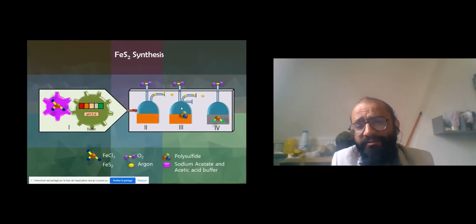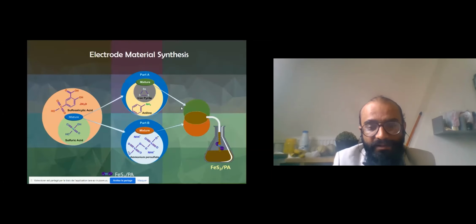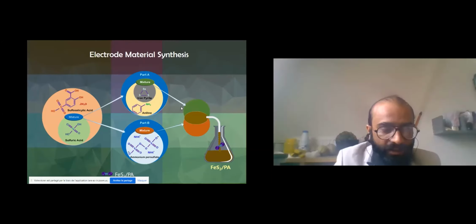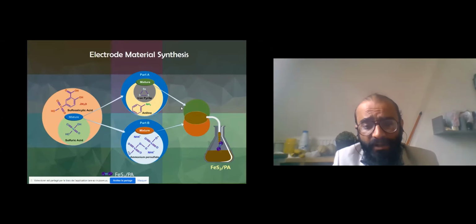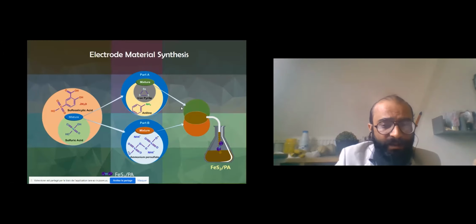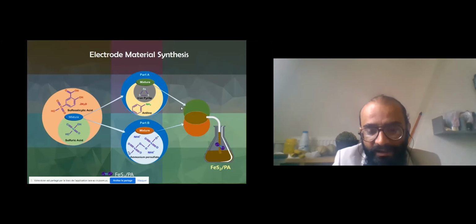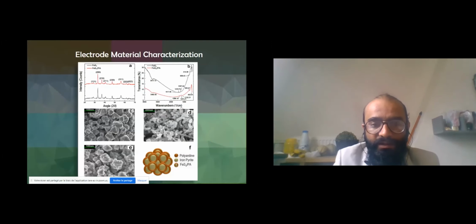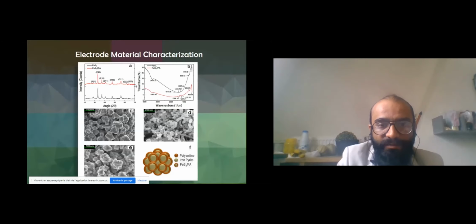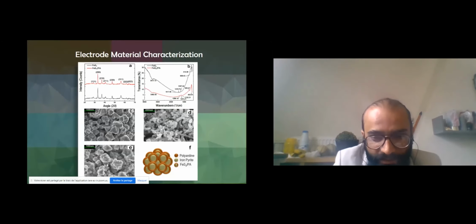You can have different kinds of reaction processes, but it is a very easy process. A very positive thing is that you can polymerize it also. If you have iron pyrite FeS2, you can polymerize it. Here I have polymerized it with polyaniline, and you can add the advantage of polyaniline too. If you use polyaniline or other polymer materials standalone, or iron pyrite alone, maybe neither has that level of efficient capability. But if you polymerize them, you can get a different result. Here we performed the electrochemical testing for FeS2, and just see the flowery kind of shape.